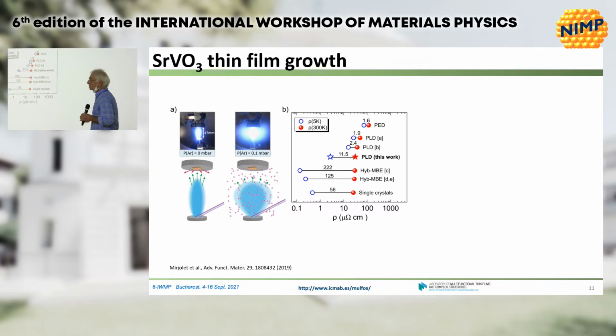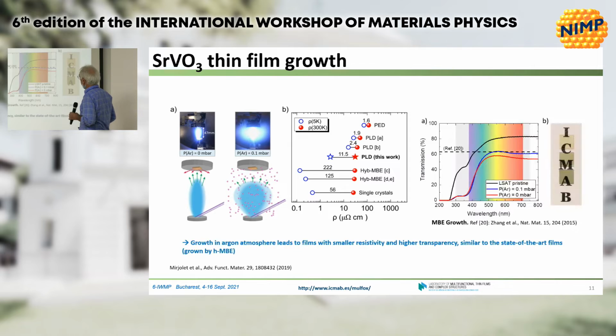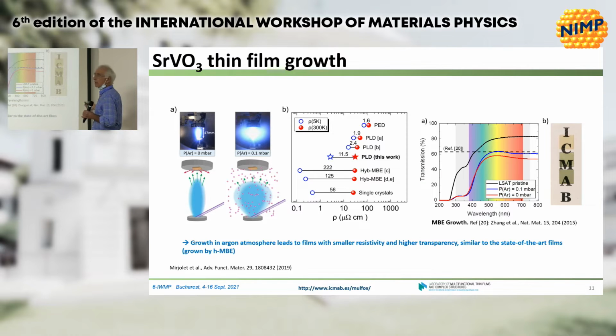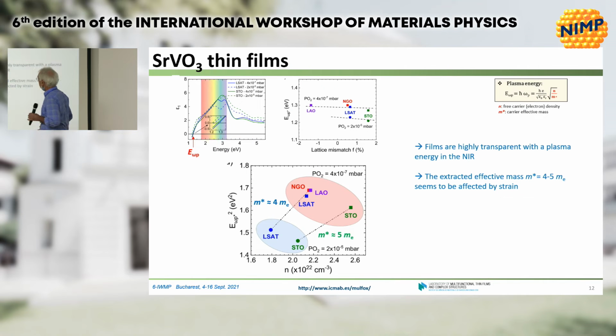So we do have now a way to obtain films with room temperature conductivity of strontium vanadate that is almost the same as platinum, and with a low temperature resistivity comparable, I would say, to MBE. So we do have the films, and those are transparent. This is the film from MBE, and depending on the growth conditions, we can get more or less transparency. And these are examples of the films.